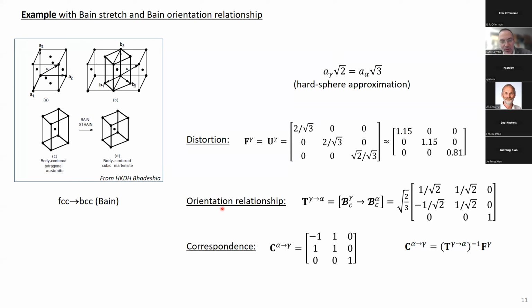Okay, you can do the calculation of the orientation relationship matrix here, and it's more or less a rotation of 45 degrees between this cube and this cube. It's 45 degrees along the c-axis. And okay, you have to take into account the volume change. That's why you have this factor in front of the matrix.